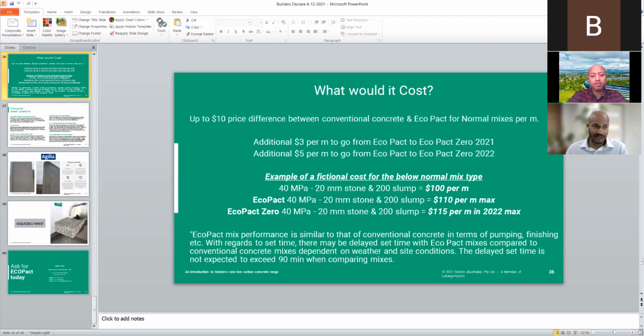But keeping that in mind, we are very confident that you wouldn't expect to see a couple of hours for concrete to go off. You're looking at maximum up to 90 minutes, like for like. So we're not expecting people's projects to blow out further than required. But saying that, you can offset some of these using accelerants, using hot water, and so forth. Shashank, did you want to add anything further to that?